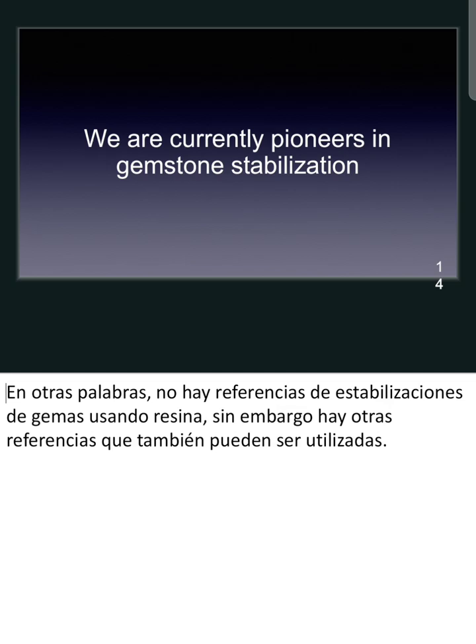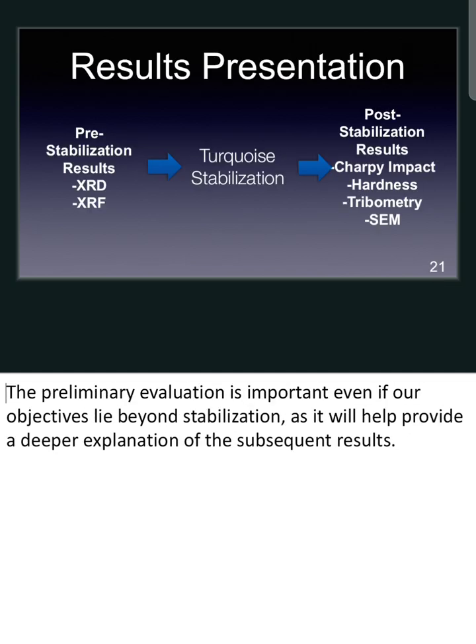Before proceeding to the results, we have to clarify that we are currently pioneers in gemstone stabilization. Now, the results presentation will be divided in three parts. The first part will be pre-stabilization results, the turquoise stabilization itself, and the post-stabilization results. In the pre-stabilization, we have XRD diffraction and X-ray fluorescence. And in the post-stabilization results, we have Charpy impact tests, Vickers hardness, tribometry, and scanning electron microscopy.